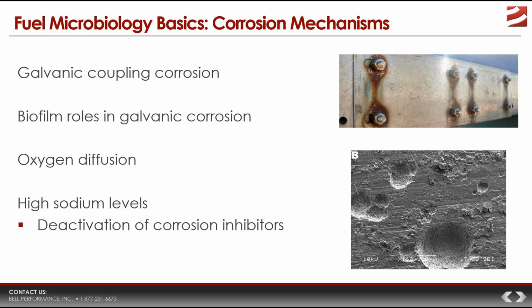Remember, way back when we mentioned sulfate-reducing microbes, sulfate-reducing bacteria, and we said they play a significant role in tank corrosion. Well, this is one of the ways that they do that. They help the formation of galvanic couples, which causes accelerated corrosion reactions to happen. Now, the presence of biofilm on metallic surfaces also plays a key role in promoting corrosive damage. That is why it is so important to address and get rid of biofilm. A lot of people think, biofilm doesn't matter as long as it's not plugging my filters, it's okay. Well, it's not okay because biofilm plays a key role in tank corrosion damage.